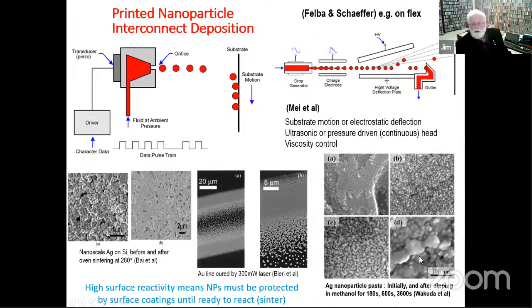We had a little lab experiment that we ran. Didn't have any controls on it, so there were no really experimental results. But you can get silver nanoparticles, particularly with coatings that are soluble in alcohol, as here, or water. And so we would have these particles with water-soluble coatings, and at room temperature, it took about 3 minutes before the resistance of an aggregate of these particles printed like this would drop dramatically, as the coatings dissolved away and the nanoparticles sintered at room temperature.